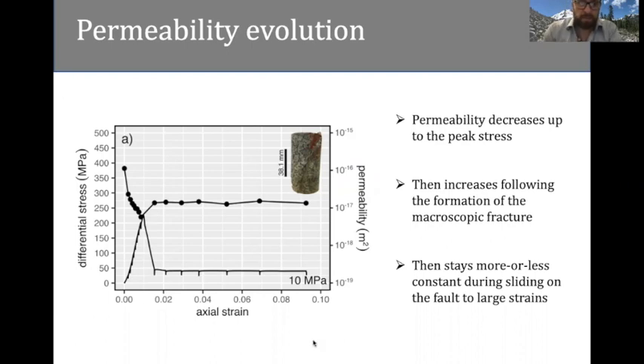So this is an example of the data for the experiment performed at 10 megapascals. So what we can see is the stress strain curve that I described earlier. And these points here are the permeability data. So what we can see is that as the sample loads up to the peak stress, we see that the permeability decreases by approximately an order of magnitude here.